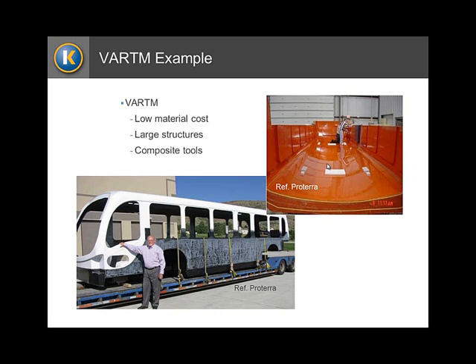Now, VARTM is vacuum-assisted resin transfer molding. The application I actually show here is more of a VARI, V-A-R-I, vacuum-assisted resin infusion, to be more accurate as far as the pictures I show. But both these processes start with, up in the right corner here, a tool, a mold. This is a huge mold of a bus body. And you lay fabric into that, dry composite materials. You put a vacuum bag on there to encapsulate it. And then you inject resin.